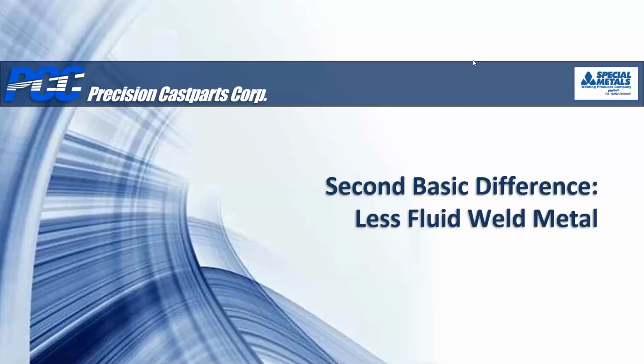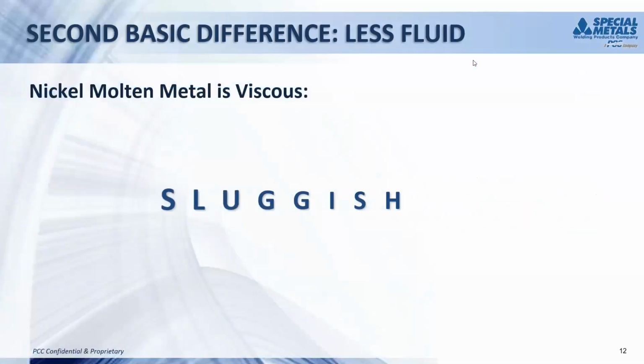The second basic difference is the less fluid, or more viscous, nickel alloy weld puddle. So we have to change gears again. We have to consider that the nickel molten metal is more viscous than steel. In fact, quite a bit more viscous. One of the comparisons that we used to make is that nickel weld metal is like cold molasses or cold syrup, versus water, the steel. So the water flows easily and quickly, and the molten nickel metal is more viscous. Next slide.